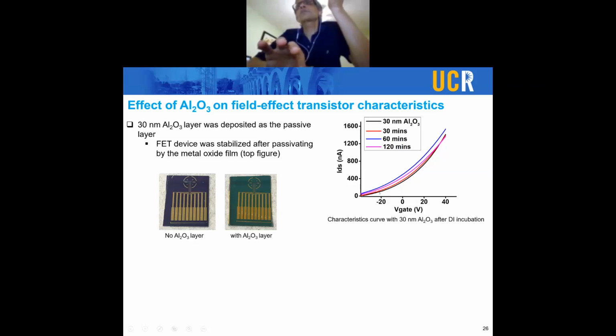And then after testing the same thing as we were doing before, the FET characteristics at 30, 60, and 120 minutes, we found that we were not seeing any more that steep drop of the source drain current, indicating that the sensor was not seeping in the water and the delamination of MoS2 was not going on. So our aluminum oxide layer was preventing this phenomenon.